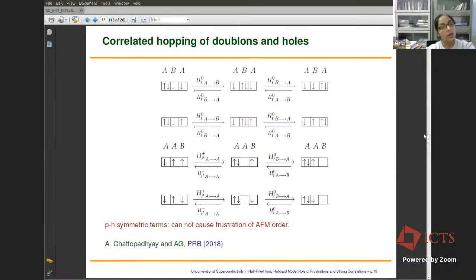Now, these terms are also kind of providing a next nearest neighbor hop, a second neighbor hop within A and within B sublattice for the doublons on A sublattice and the holes on B sublattice. But an important point to keep in mind is that these terms are particle hole symmetric and they do not cause any frustration of the antiferromagnetic order. So these kind of terms, first of all, are highly suppressed compared to the bare second neighbor hopping terms, and these terms will not help us in stabilizing the superconducting phase, as we will see after some slides.